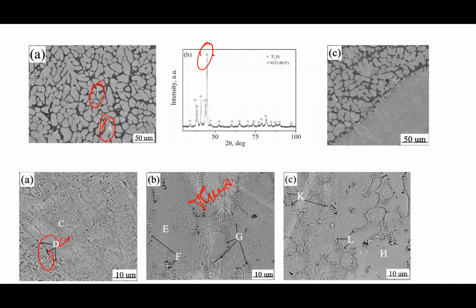So the fourth layer has a structure similar to the third layer. However, the dendrite matrix has a chemical composition of titanium with 50.9% of Ni, and the volume fraction of Ni rich NiTi phase in the interdendrite space could be achieved. So now, if I talk about the fifth layer, so this is my fifth layer. In this fifth layer, the interdendrite space does not contain any Ni rich NiTi phase, and in this layer, the dendritic matrix is a Ni rich NiTi phase, with a Ni concentration of 15.9% marked as K.